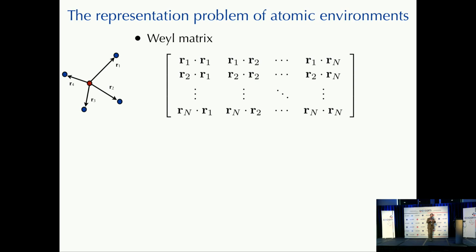So how do we represent, systematically and in a many-body way, the neighborhood of an atom, which we can then plug into one of these regression methods? Suppose that you have this atom whose energy I want to fit, and it has a bunch of neighbors, maybe 4, maybe 20, and I want a description of its many-body neighborhood in a continuous, systematic way, but also one that obeys symmetry. So if I permute two atoms that have the same nucleus, I don't want the energy function to change. If I rotate this entire system in the lab frame, I don't want the energy to change.